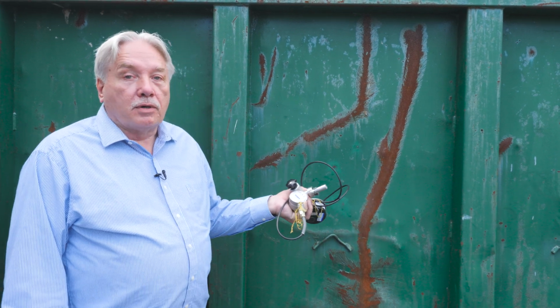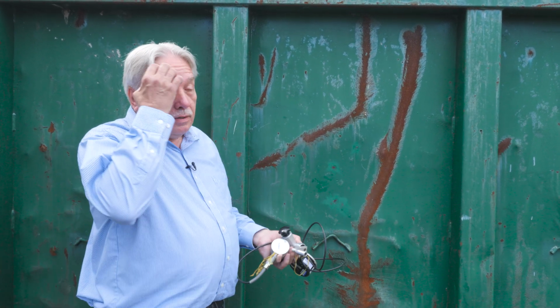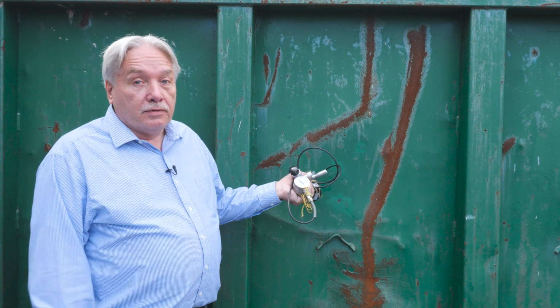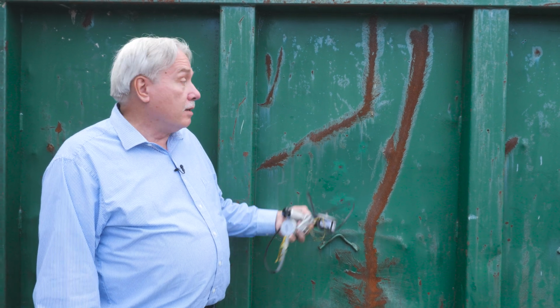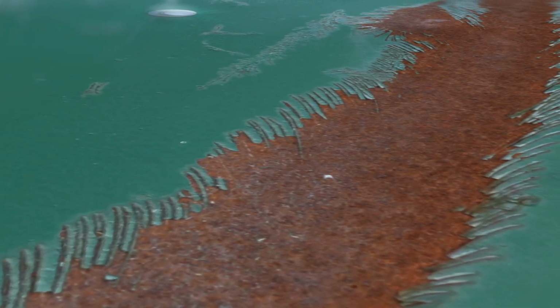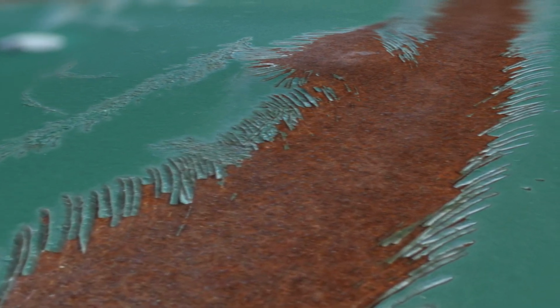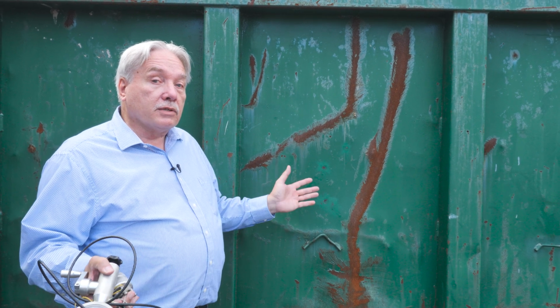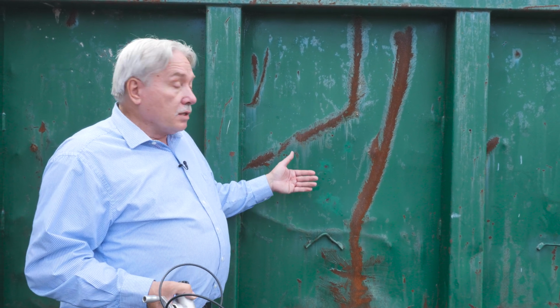So in this particular instance where we've been looking at some coated steel here, obviously this isn't a spring chicken, and this has been around for a while. So our customer might be interested in repainting this. We just performed some adhesion tests. We had some values that were all above 500 PSI. And so that would be indicative of good adhesion.